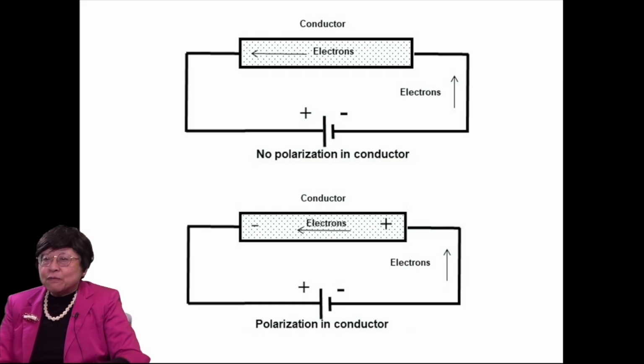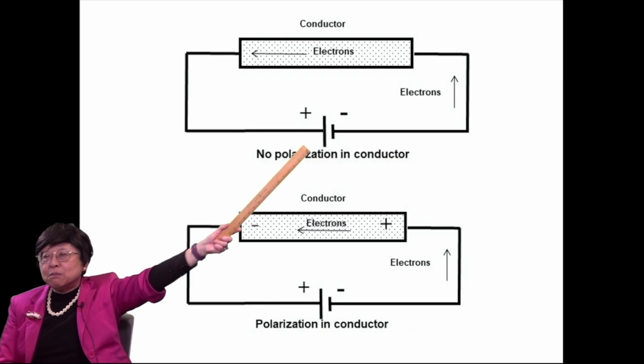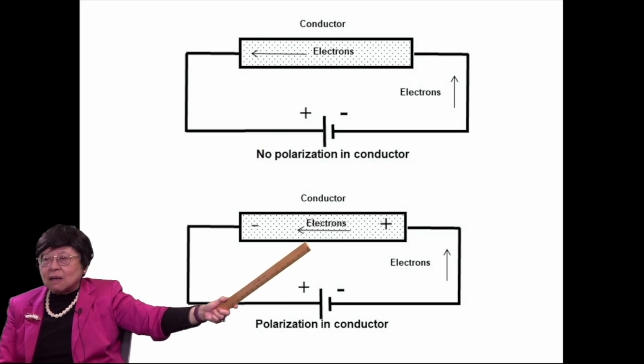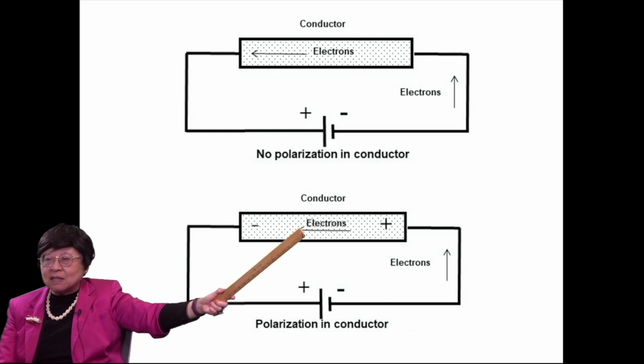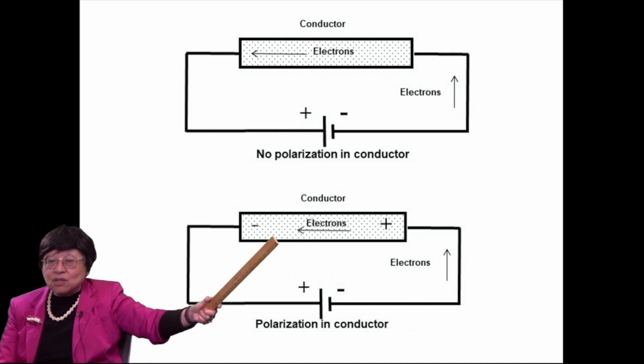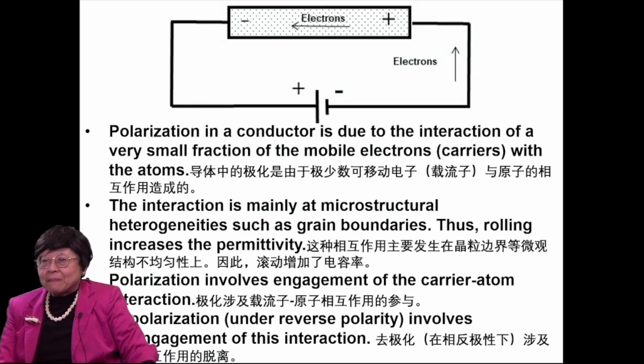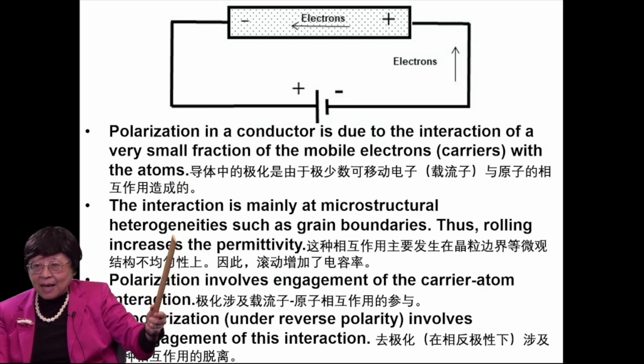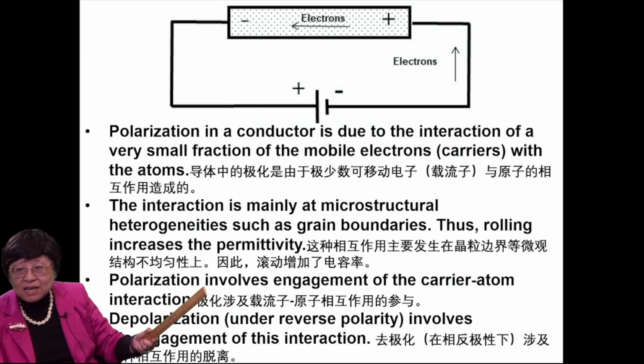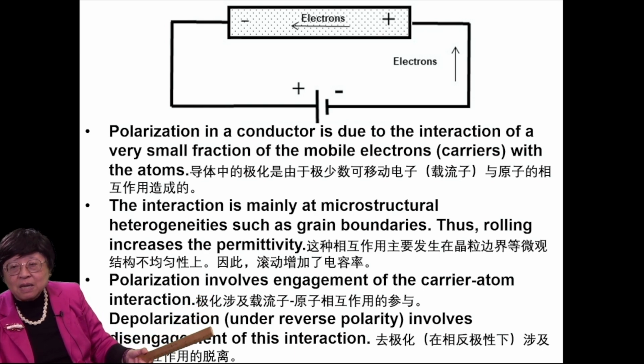Okay. Now, for a conductor, if the electrons just move around without interacting with the atoms in the conductor, then there's no polarization. But if the electrons, at least a fraction of the electrons, interact with the atoms in the conductor, then there would be polarization. Okay? So polarization in a conductor requires a degree of electron-atom interaction. And it turns out that it's just a very small fraction of the mobile electrons interacting with the atoms. And the interaction is mainly occurring at microstructural heterogeneities, such as the grain boundaries. Thus, rolling increases the permittivity. Polarization involves engagement of the carrier-atom interaction, whereas depolarization under reverse polarity involves disengagement of this interaction.